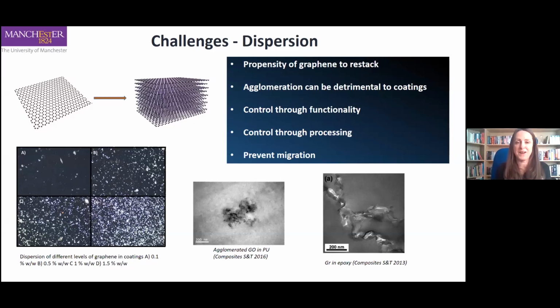Graphite's happy being graphite. We go to all this trouble to make these 2D materials, but then we mix it with something, and the tendency is for the graphite to want to restack. It's got all this surface area and these van der Waals forces. It wants to go back to being graphitic-like. So this is a problem because you can get large amounts of agglomeration when you mix graphene into different systems and different coatings. So you really have to start thinking about processing techniques.